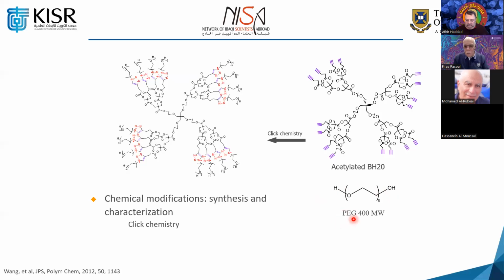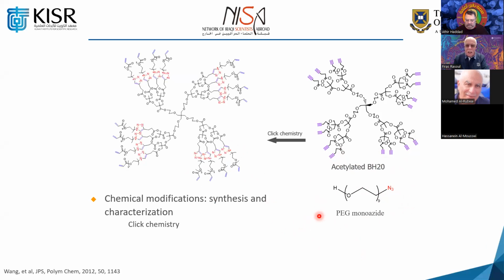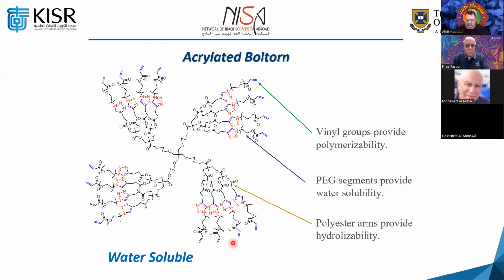we took a polyethylene glycol, again 400 molecular weight, 9 repeated units of ethylene oxide. And what we did with that, we converted it to azide. And of course, we have the acetylene group here, and the azide, we did some click chemistry, the normal nice click chemistry, as you see here. Then after clicking this, we functionalize it with acryloyl chloride, and we convert it to a polymerizable acrylate group.